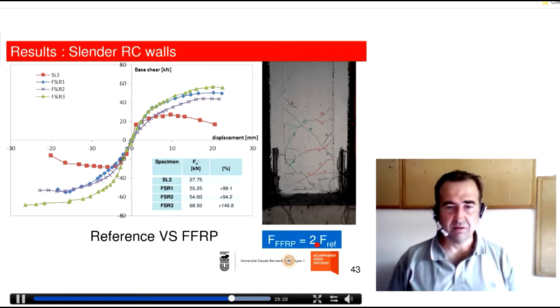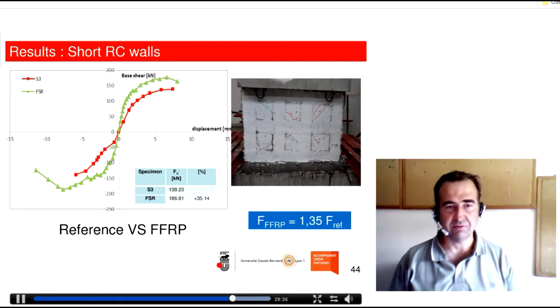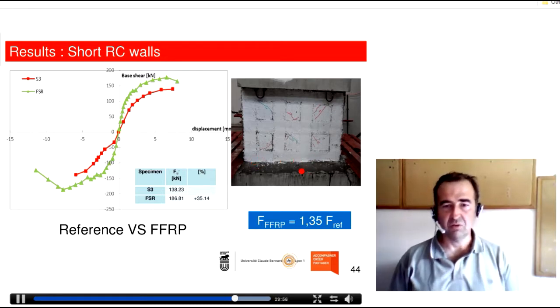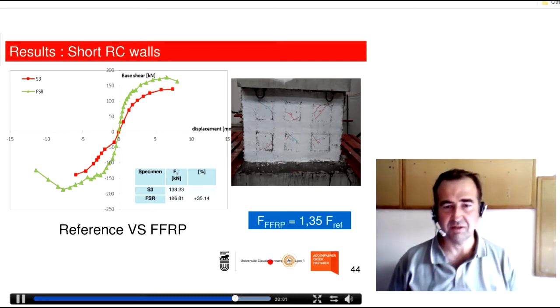At the end, we obtain a capacity thanks to a horizontal load which is twice in comparison with the reference specimen. For the short walls, the increase is lower, but the load is very high. And we obtain a 35% increase in shear, but what we get in this wall is a very premature failure at the basement, with a sliding between the wall and the basement, so we didn't get the real full shear capacity of the wall.